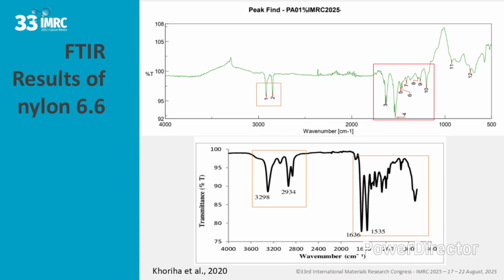Bands between 1630 and 1530 cm⁻¹ correspond to amide I, C=O stretching, and amide II, N-H bending coupled with C-N stretching, characteristic of the peptide bond present in polyamides, are visible. The region between 1200 and 600 cm⁻¹ presents several signals associated with C-N and C-C vibrations, typical of the polyamide backbone. Bottom, black spectrum.